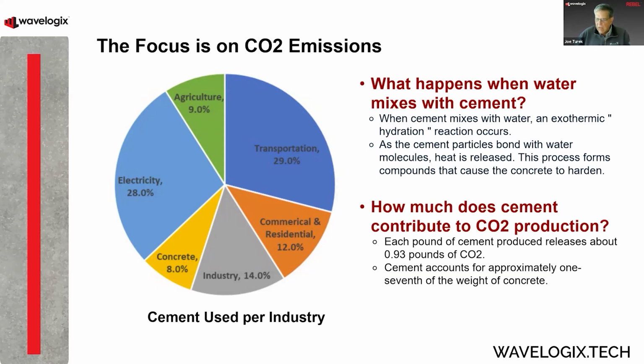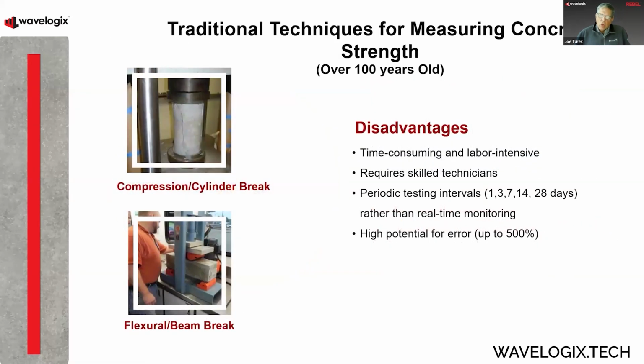And because of that, every pound of cement releases about 0.93 pounds of CO2, almost a 1-for-1 in cement. And again, as I said, cement accounts for approximately 1/7 of the total weight of concrete. So why is that important, and what happens in concrete?